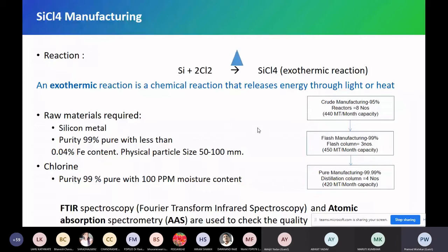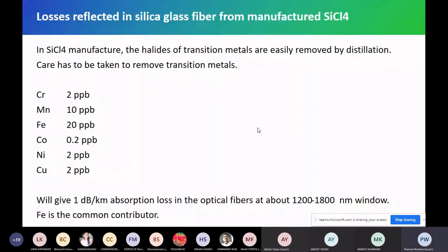And just for your glimpse, if we have chromium ions, just 2 parts per billion, or iron, 20 ppb, parts per billion, just 20 ppb of iron can give 1 decibel per kilometer loss. See, 1 decibel per kilometer. We are talking about 0.2, 0.18 decibel per kilometer loss, so 20 ppb is not negligible, right? 20 ppb can give huge losses in optical fiber. So that's why containing this metallic contamination is very important. With contamination, you're going to spoil all the optical fiber. You cannot save it. Nobody will purchase the optical fiber.